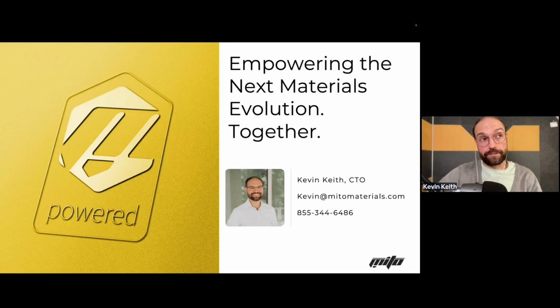Yes and no, there is a difference. If you were to plug in just a bottoms-up graphene into a composite, you're going to have a lot of difficulty getting that to be well dispersed. We do see that with our functionalities, it's much easier to disperse. And whenever we compare apples to apples a functionalized version to a non-functionalized version, it's leaps and bounds. With non-functionalized bottoms-up at 0.1%, you actually have a decrease in properties, about 5 to 10%.